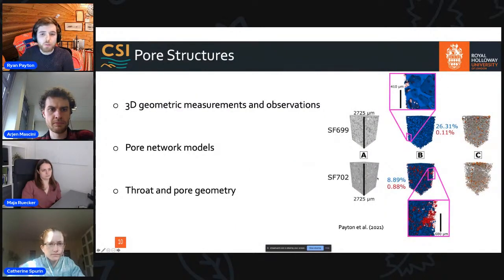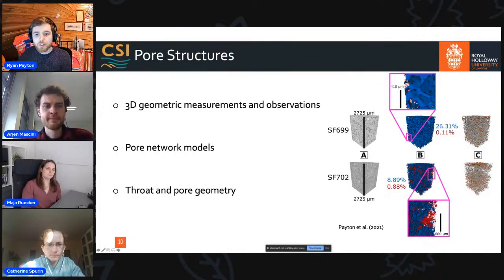So we're also able to describe a few other things in a more qualitative sense to then derive some more quantitative results. So from these image stacks, we're able to extract the total porosity, which you can see in blue. And then in red, you can see just about up here, these tiny little speckles are the disconnected porosity. Now, in this case, we can see that the majority of the disconnected porosity is actually intragranular. So where these voids are left where the grains are, which have been segmented out, this is where the majority of the disconnected porosity is forming.